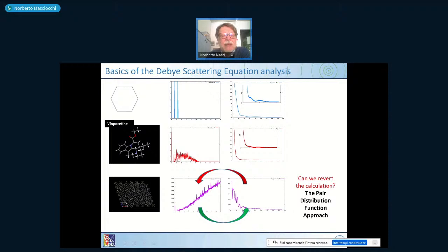These peaks you see here are those which give information on the structure. It's not a flat curve, it's not a smooth curve, it's a curve which has a few peaks. These peaks translate themselves into the curve we've seen before. Again, if I do the same computation for an older, larger system, the histogram plot shifts much to the right because you have a larger system. And again, some peaks here are not just noise, they are structure information: some distances occur much more frequently than others. And they are translated by the Debye equation into a scattering pattern.